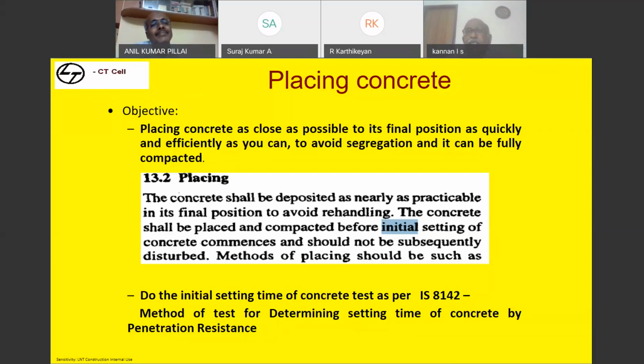So my request is, whatever you are placing, please see that the concrete goes in place before the initial setting time of concrete commences. Suppose when you do the test as per IS 8142 and you are getting an initial setting time of 5 hours, keep 1 hour less, because 5 hours is in the lab. Keep 4 hours. Within 4 hours, the concrete should go in place. Or if it is 4 hours, within 3 hours it needs to go in place. Consider that and design your mix so that the concrete we produce goes in place without any difficulty, so that we are not allowing anybody to retemper the concrete at site. If you are able to give a highly workable mix, why would people add water?